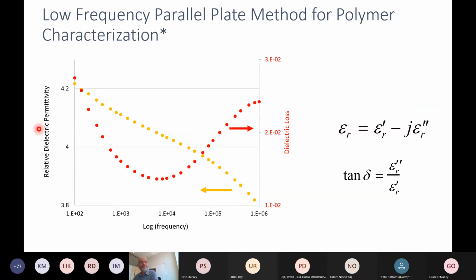Here we're plotting the permittivity that is shown here. And here's the dielectric loss shown here in these red dots versus frequency going from 100 hertz to a megahertz. And we could already see something interesting is happening where we see this decrease in the permittivity and we see this change in the loss of the material. I'll talk a little bit about the polarization mechanisms in future slides, but you can learn a lot just in this frequency range and then build upon this knowledge when you start doing higher frequencies.